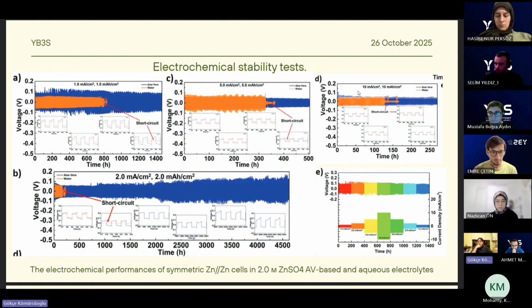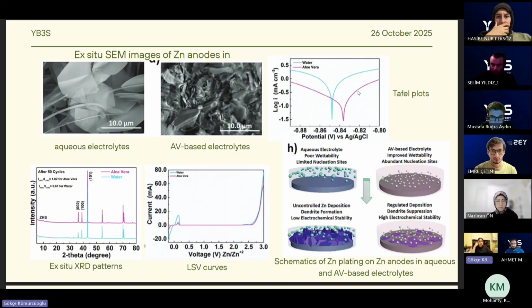And also at the last picture, we see its behavior at different current densities. In this first picture, they used SEM to look at the aqueous electrolyte and the aloe vera-based electrolyte. In this first picture, we see that dendrite formation happened, and in the right picture, we see that it is much less.